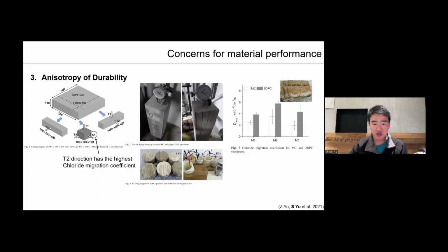So anisotropy doesn't just affect the strength, it also impacts the durability. We conducted durability tests in different directions of the samples, and here is one example, the chloride migration test. In this case, the T2 direction, which is the side of the filament, shows the highest chloride migration coefficient. This means it is the weakest direction in terms of chloride resistance.